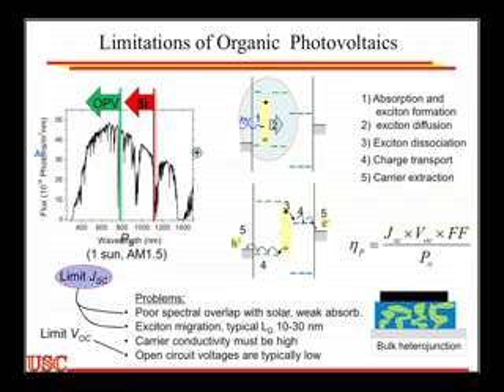And so what it means is that if I think about this diffusion process, step number 2, if my organic layer is thicker than, say, 30 nanometers, it doesn't matter how thick I make it after that, because none of the light absorption will lead to excitons that get to the interface. Remember, only excitons reaching the interface are useful. The rest of them are wasted. And so it limits the amount of material so that you can't make your devices very thick, at least in that lamellar structure I showed you before.